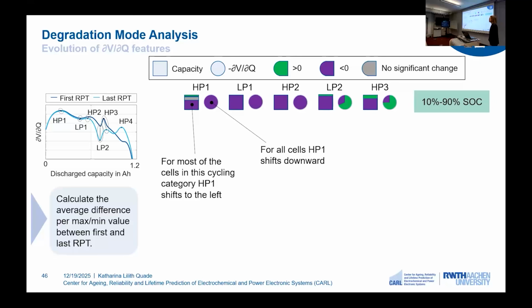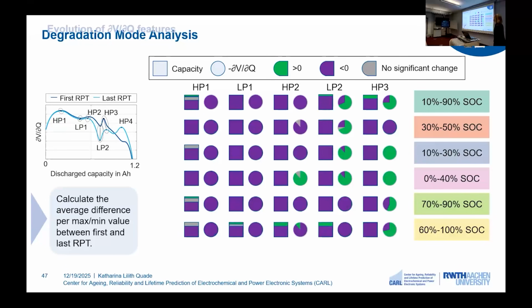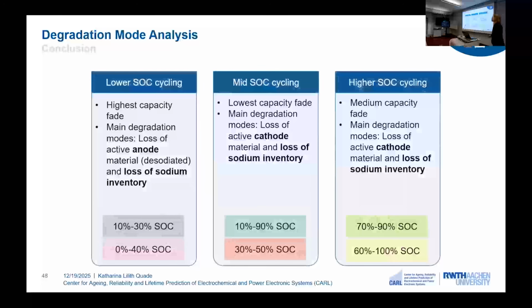And again, we do this for all other peaks and for all other categories. And here you can see the issue that we have with the different aging trends. When we now focus on HP3 in the category 70 to 90% SOC, we can see that only 60% have a clear trend where the shift goes upward, and for the other 40%, the peak shifts downward. However, we analyze the agreement between the theoretical peak shift and the peak evolution for each category. And here we only focus on the main degradation modes. And here we can see the results.